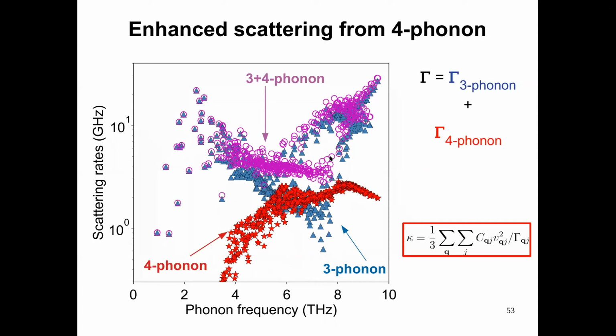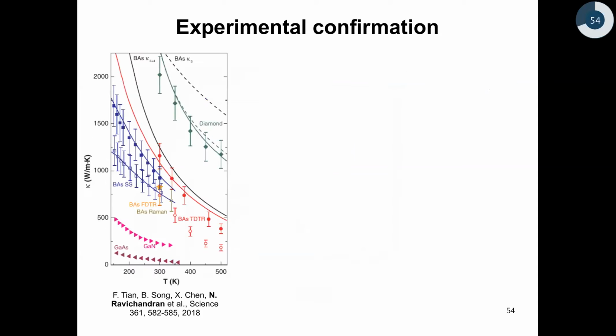So there's a dramatic increase in the total scattering rates by addition of 4 phonon scattering. The denominator is going up in this thermal conductivity expression, so the thermal conductivity is dropping down. And this is the microscopic origin for why 4 phonon scattering is having a dramatic effect on thermal conductivity. Okay, so these are just computations, right? So how do we know these things are actually happening in reality?